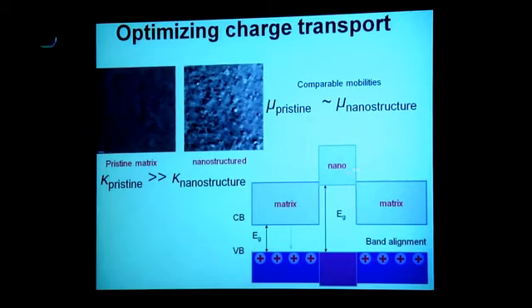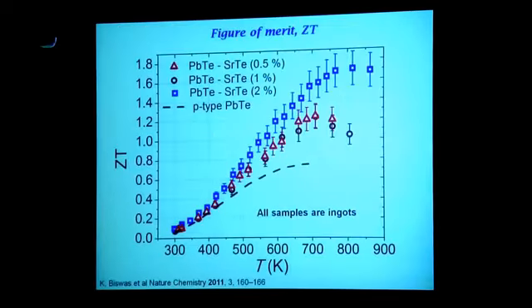If you're an electron, it's a different story. If you're an electron, you have to overcome this huge barrier. And indeed, when you dope these things n-type, the mobilities drop. You lose the mobilities because of the scattering that you see there. We have these two good effects. You can combine them, you get a very high ZT at the 2%, closer to 1.7 or so, which is a record high number. That essentially tells you that this is a great approach to engineer the bands and the nanostructures such that you get maximum effect on the thermal conductivity, but not on the power factor.